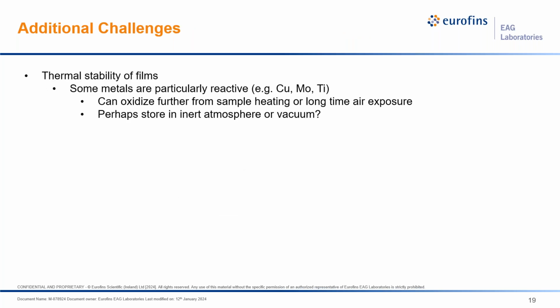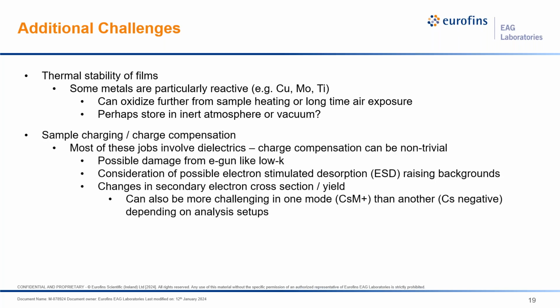So what other considerations or other challenges do we have? The films themselves might not be thermodynamically stable. Some metals in particular are very reactive. So for example, copper, moly, titanium will already start oxidizing with exposure to air, and then the additional heat can even be worse. So sometimes we have to consider whether or not to store the samples in an inert atmosphere or under vacuum or in some other controlled way rather than just normally in the lab somewhere.